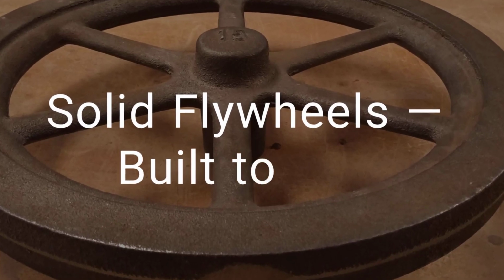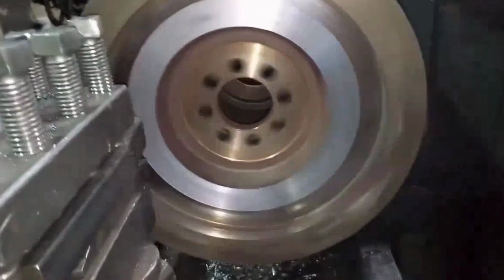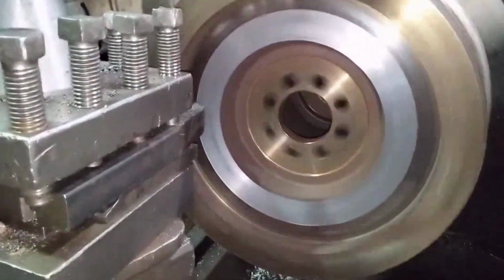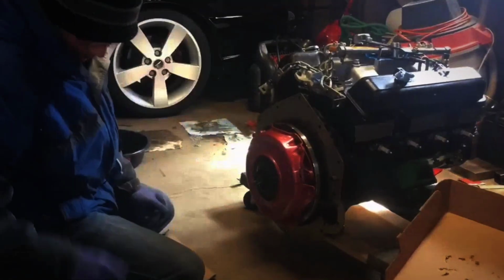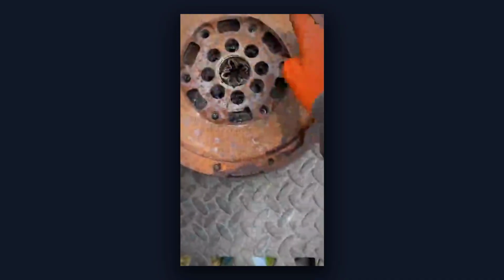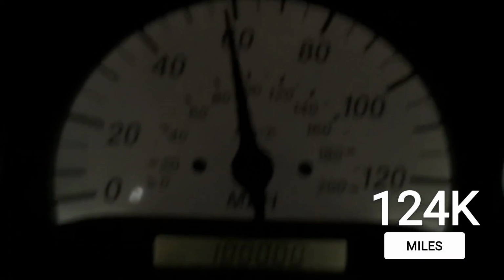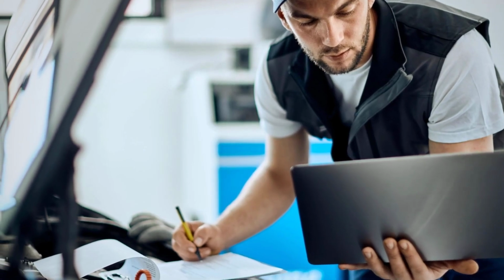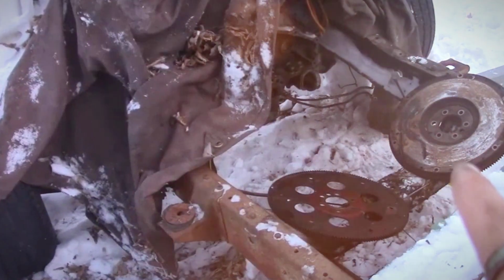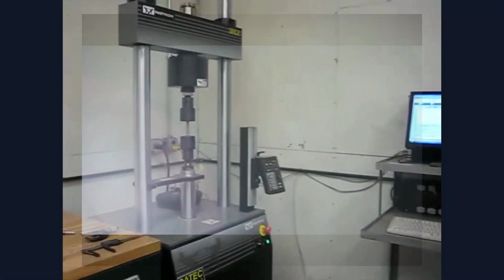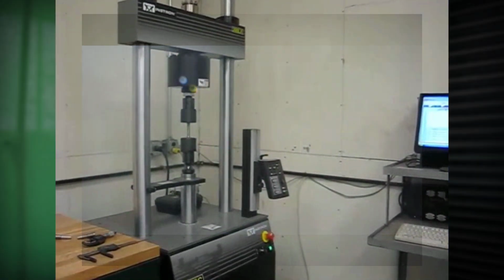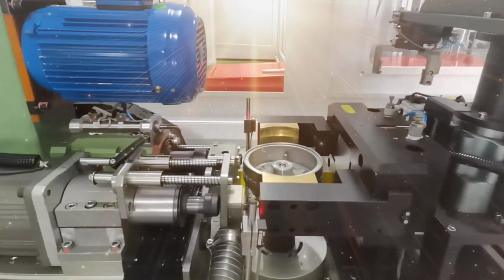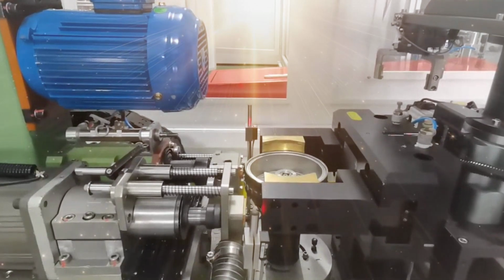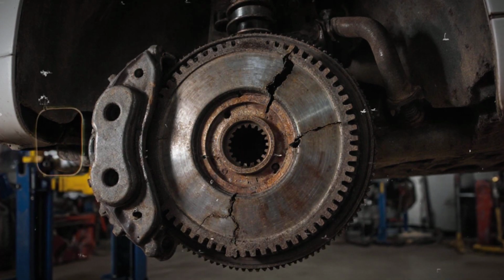In 8th place, solid flywheels are the definition of mechanical simplicity, just a single forged or cast iron disc, often EN-GJL-250, that shrugs off hundreds of thousands of clutch cycles without complaint. Unlike dual-mass flywheels, which introduce a spring pack and typically fail between 112,000 and 124,000 miles, according to APSA's 2023 Repair Shop Survey, the solid design has no internal wear points. The tensile strength of these discs matches that of cast iron engine blocks, 250 to 350 megapascals, leaving a wide margin over any stress they will ever see. Failures are rare and usually traced to severe abuse or visible cracking, not gradual wear.